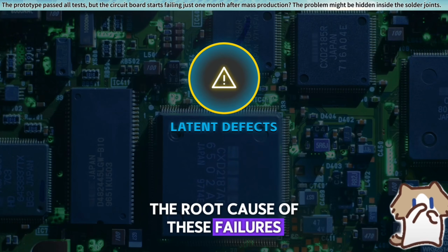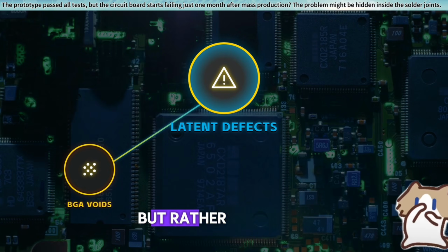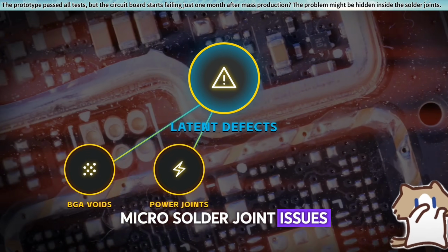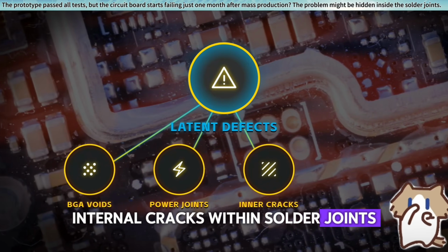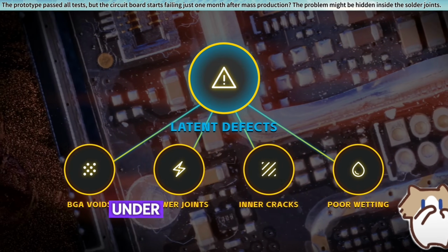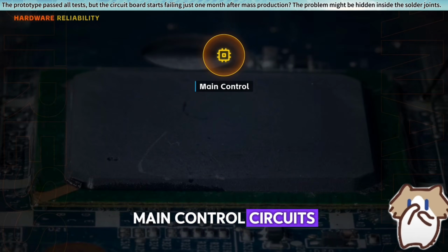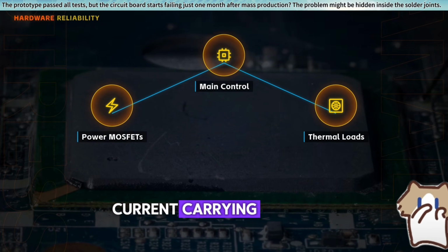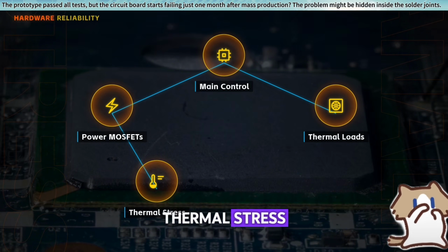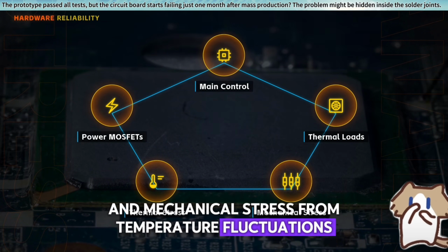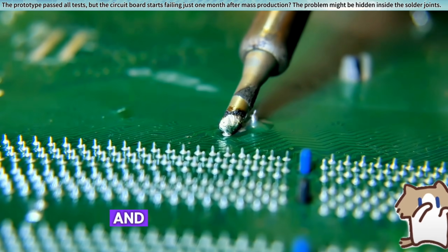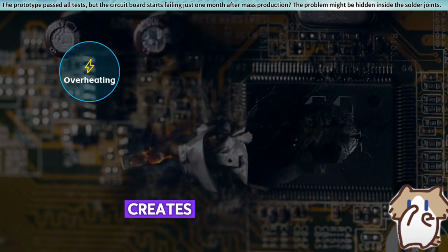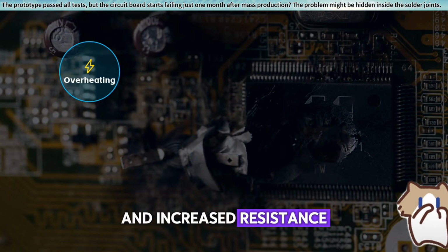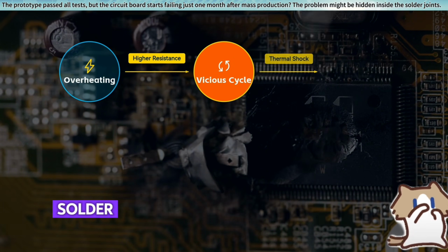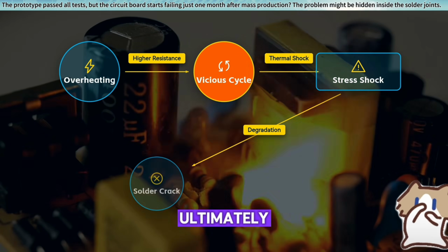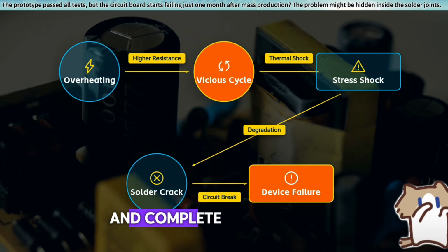The root cause of these failures is not visibly obvious solder joint defects, but rather BGA voids, micro solder joint issues in power devices, internal cracks within solder joints, and localized poor wetting. Under the combined effects of high current main control circuits, power MOSFETs, current carrying loads on thermal pads, thermal stress, and mechanical stress from temperature fluctuations, these voids reduce both conductive and thermal surface areas. Prolonged operation creates a vicious cycle of overheating and increased resistance. Coupled with thermal shock and vibration, solder joints progressively deteriorate and crack, ultimately leading to interruptions in the power supply circuit and complete device failure.